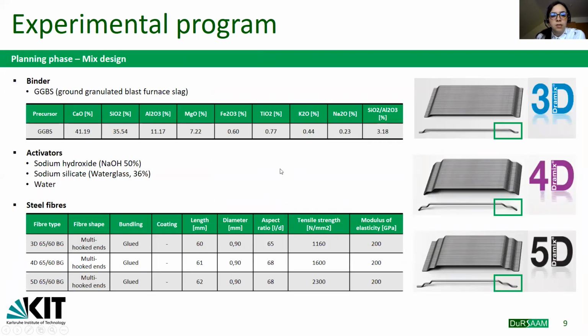In the planning phase, after different trials, a good workable mix with a good setting time and a compressive strength higher than 30 MPa after 28 days was developed using blast furnace slag as binder, sodium hydroxide and sodium silicate in combination with water as activators, and 3 different Dramix steel fibers were used for this investigation.